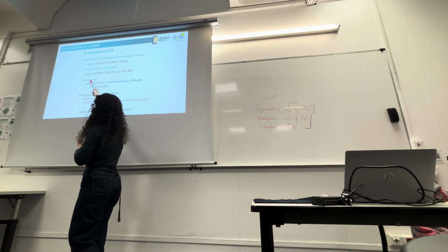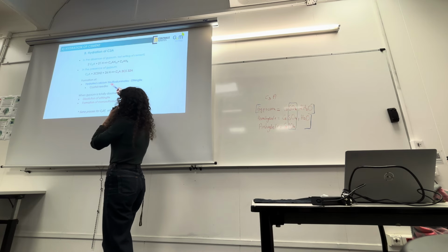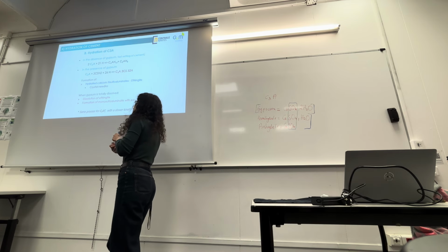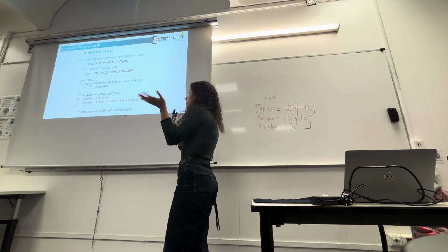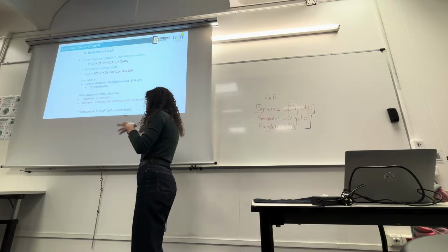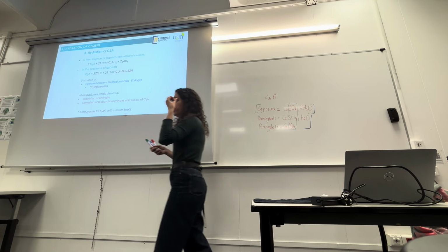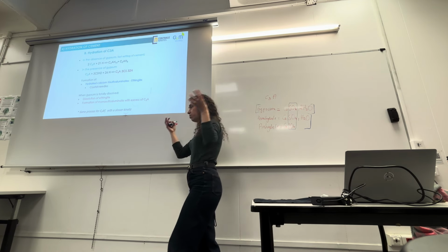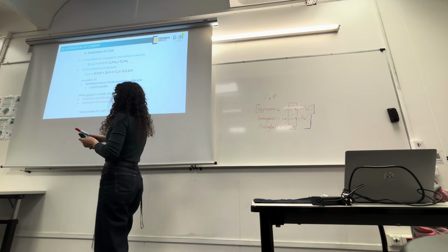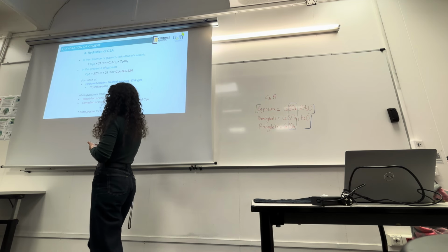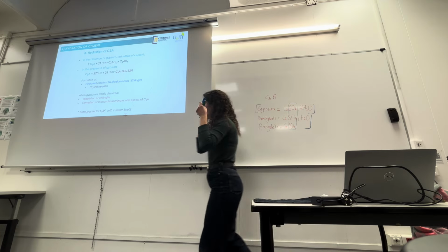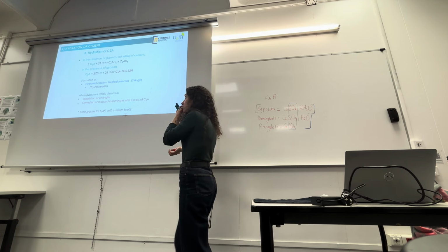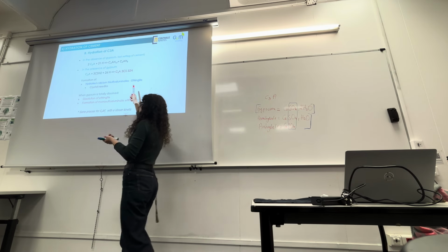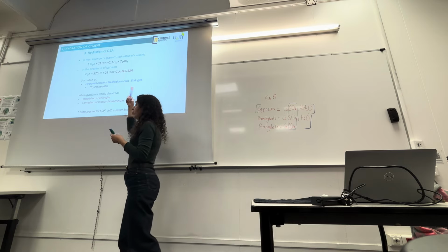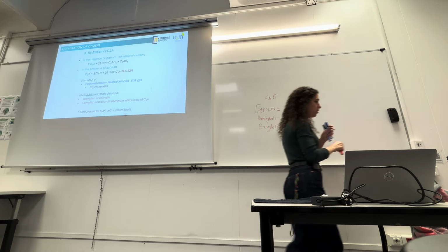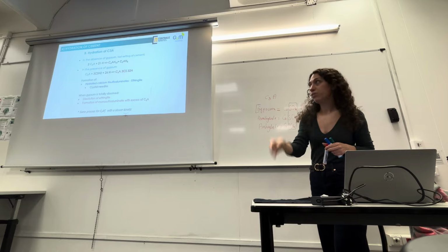So you don't have to remember the equation of the compound that is formed in the absence of gypsum. Just remember that in the absence of gypsum, of the setting regulator, you have a setting of cement that is too fast. The reaction of C3A with water is too fast. So we use the presence of gypsum to react and to form what we call ettringite. You don't have to remember the chemical formula of ettringite. I wrote all my PhD thesis on ettringite, and I don't remember myself the chemical formula of ettringite, so I won't ask you the chemical formula of ettringite. Just remember the name, ettringite.